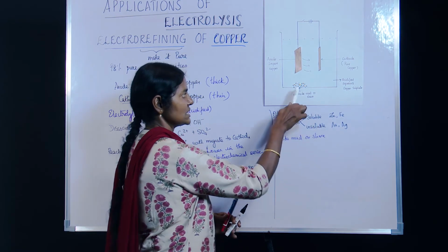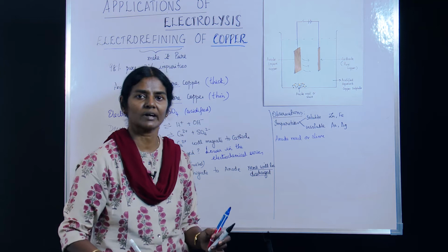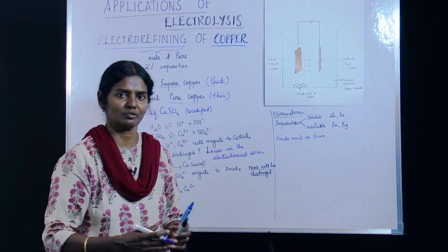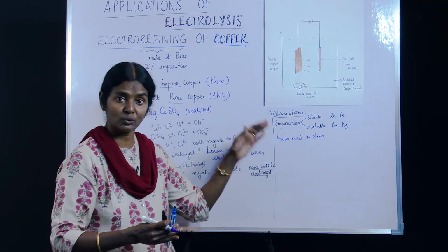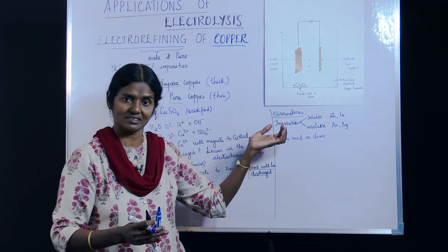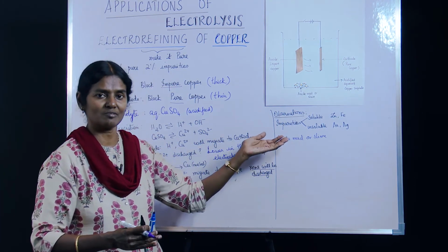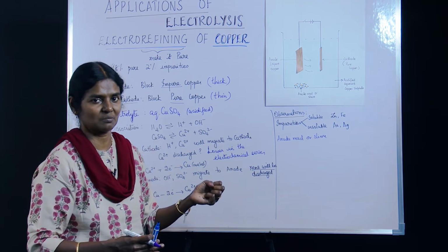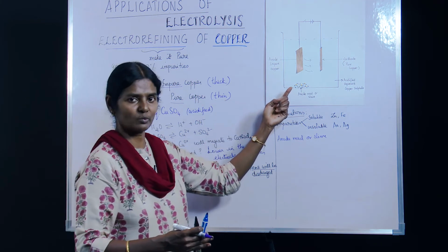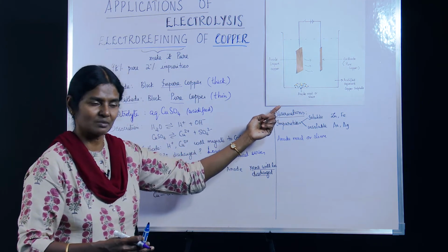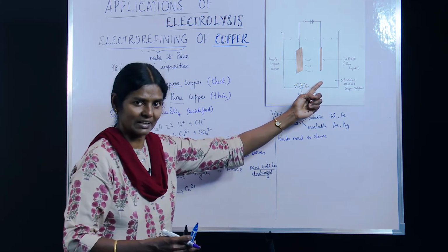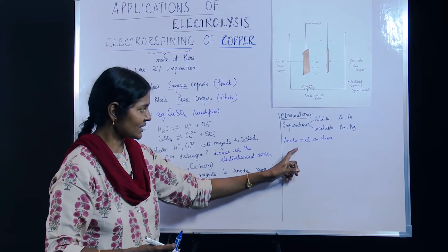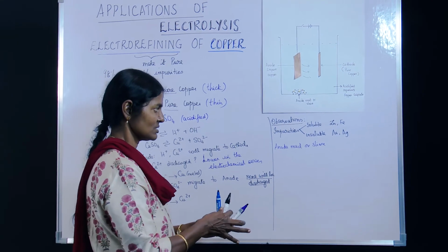You can see some bits of gold and silver metal. Would you like to just throw it away? No. When we know that some precious thing is present there, we wouldn't throw it off, but we would like to retrieve it to the maximum. This is one method where we need not waste it, because it is not dissolved in the electrolyte, but just gets deposited as a heap, and that is called anode mud or slime.